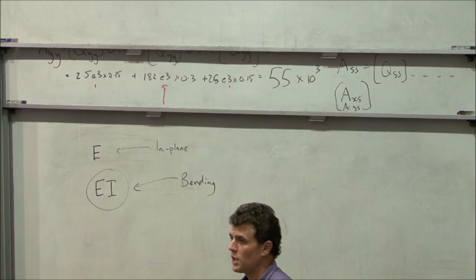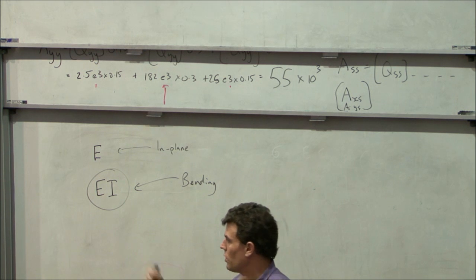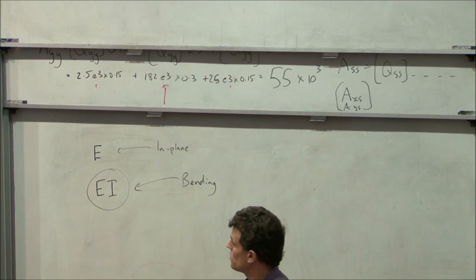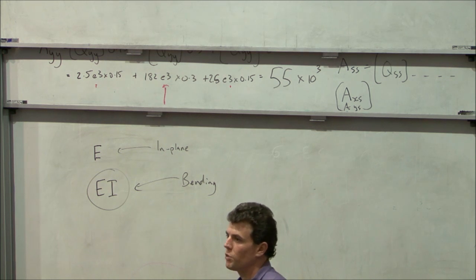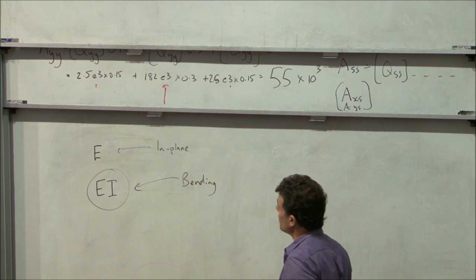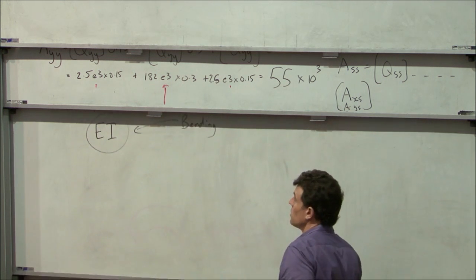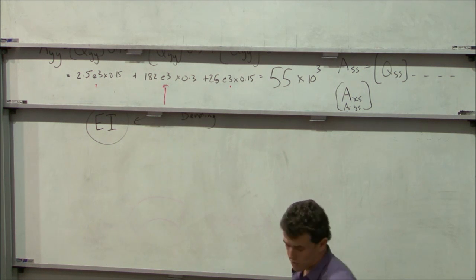So it's useful for telling us, if you've got a thin-walled structure and we want to know how stiff it is, it's very useful for that. What it doesn't tell us is how they behave if we put local bending on them. So what we need is this D matrix, which is this one.